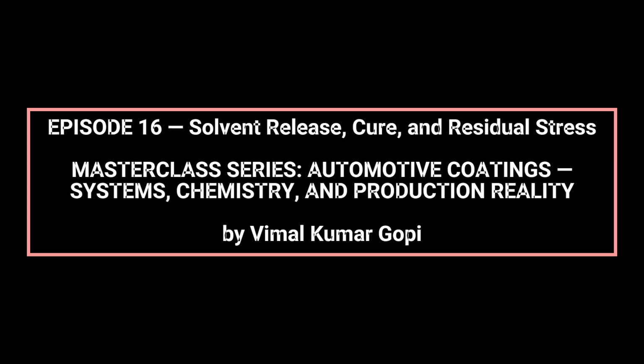Solvent package engineering to control release profiles, rheology and resin architecture to support controlled network formation, process optimization to account for bake profile, airflow, and part geometry. By managing solvent release, curing kinetics, and residual stress development in tandem, coatings teams ensure appearance, mechanical durability, and OEM approval reliability. In summary, solvent release, curing, and residual stress are interdependent processes that govern long-term coating performance. Laboratory evaluation alone cannot capture production variability, making system-level design essential for robust, OEM-compliant coatings.